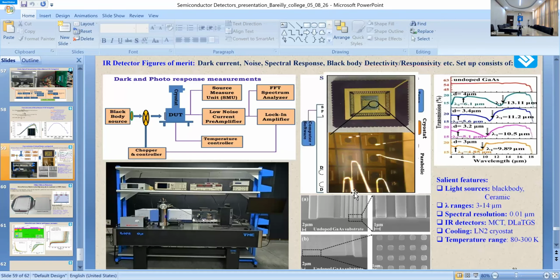For the IR detector image sensor, we mainly use this kind of measurement setup, where the source is a black body. We use a cryostat because the IR detectors are made of very low bandgap materials. Bandgaps we are talking about are 0.2 eV, whereas for silicon the bandgap is 1.12 eV. So thermal generation is very high in IR detector materials, and that's why we use cryogenic temperatures. Basically, these compound semiconductor IR detectors mainly operate at cryogenic temperatures, from let's say 77 Kelvin to 150 Kelvin.